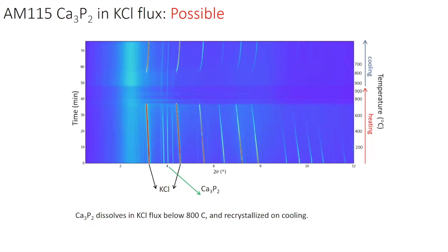So the first thing we have to do, though, is find the right flux. And so here's a picture of a diffraction pattern. So this is a function of angle. So these are each diffraction peaks. And this is as a function of time. And on the right side, you can see the temperatures that were present at each of those times.